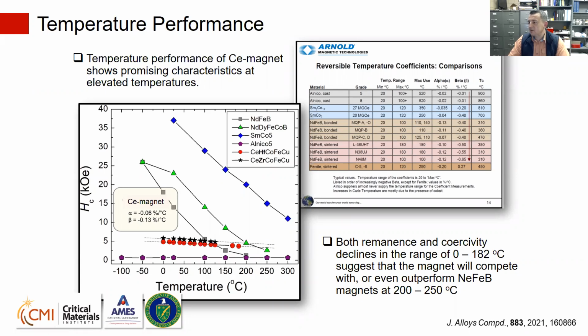Another question: what is the lowest content of cobalt you think you can get with 20 plus MGOe? I think we can get to 38 to 41 weight percent with 20 plus MGOe. Surprisingly, if we increase MGOe, we also decrease cobalt, because MGOe can only be increased with increased magnetization, and increased magnetization can only happen when you put in more iron. So basically, remove cobalt.